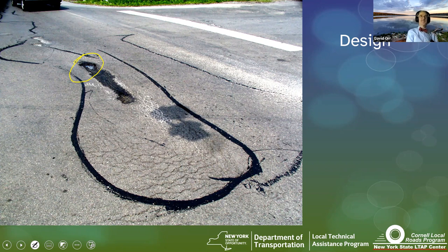Okay. But in terms of the pavement itself, let's assume we fix the drainage. Is this a candidate for a chip seal? Was it a candidate for crack repairs? I hope nobody would say yes. But maybe micropave, but be real careful. If this pavement is moving, that micropave won't last. It doesn't add any structural strength. So you may need to undercut the subgrade and replace the full section. The one thing this is definitely not is a candidate for an overlay.